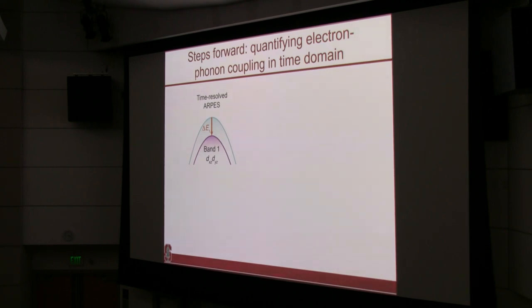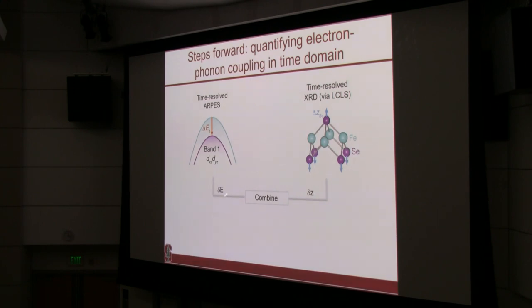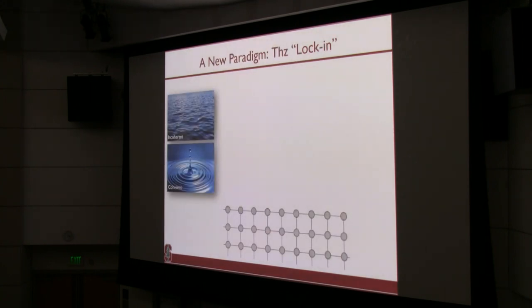And you can use the time-resolved photoemission to measure the energy level and use time-resolved X-ray diffraction to basically measure the lattice. And if you have both of them as a direct measurement, okay, lattice constant change or the energy level change, then you can make a test without having to have an input, okay? And you can do the deformation potential. So that's what we set out to do.